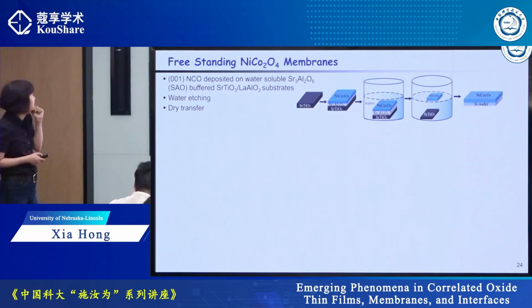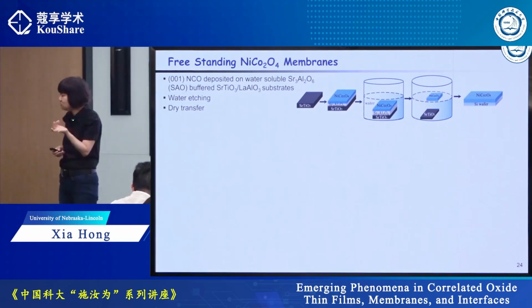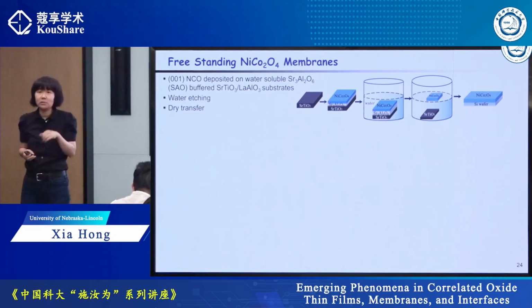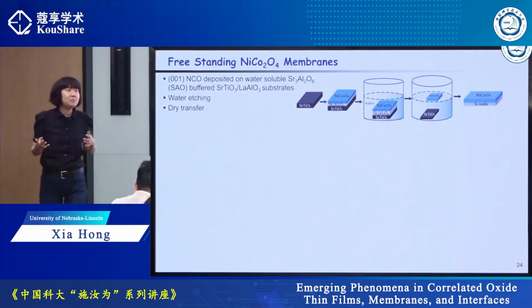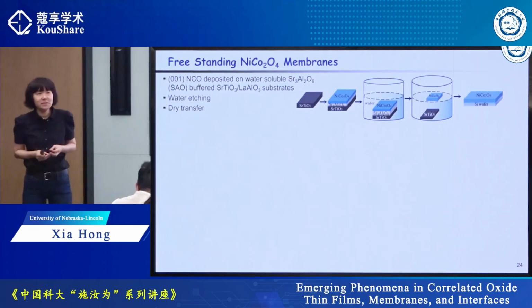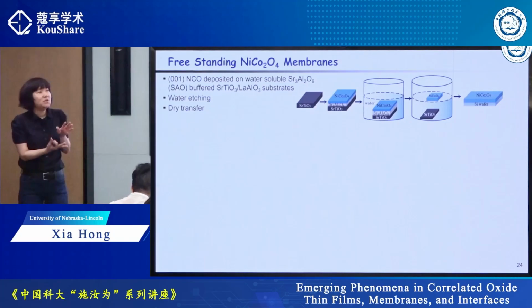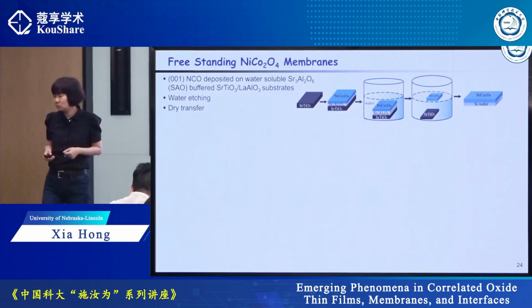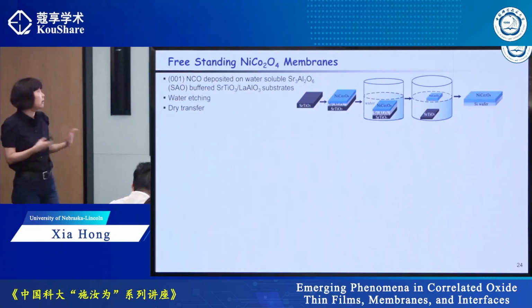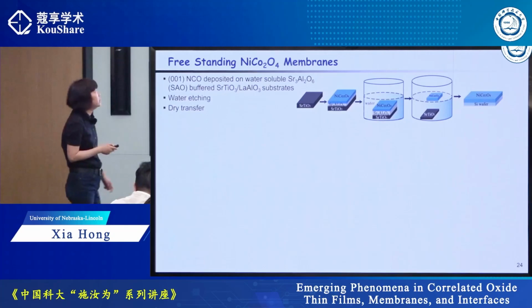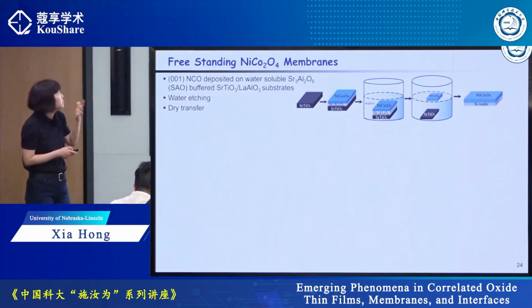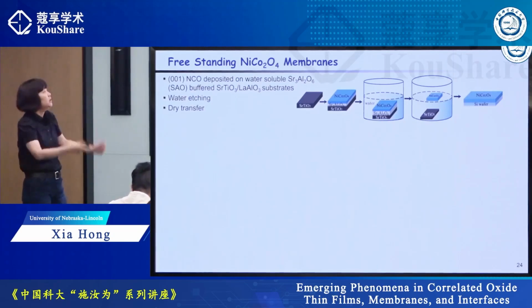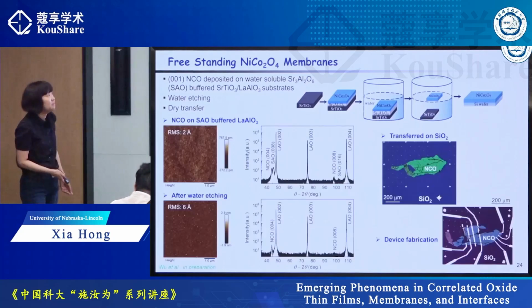Another thing we have done is for a totally different reason. We're recently interested in free-standing oxide membranes. The reason is very easy to understand, because van der Waals material has been very popular because you can exfoliate and build structures by stacking. With oxide, people think you cannot because it requires epitaxial growth. But if you can actually suspend the oxide, I can also build non-lattice matched multifunctional heterostructures. So we try to suspend nickel cobaltate by growing it on a water-soluble material, strontium aluminate, soak it in water, and then scoop the suspended flakes out.